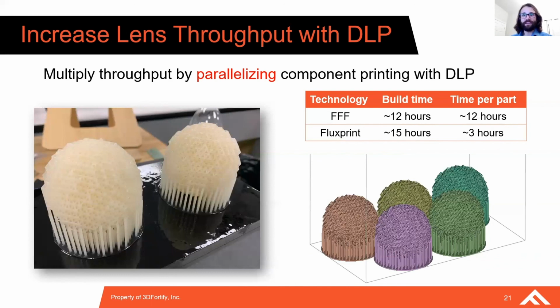Comparing to fused filament fabrication, which can take an estimated 12 hours to complete just one 62 millimeter lens, the Fluxprint can produce 5 lenses in a quarter of the time.